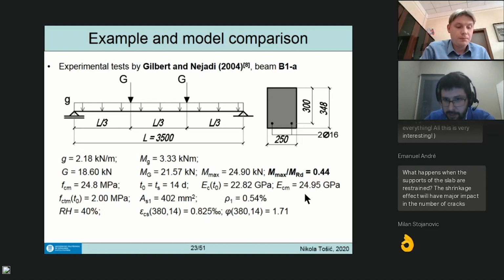Modulus measured at 14 days and at 28 days. Tensile strength measured at the time of loading, splitting, or we can approximate it to axial tensile strength. Reinforcement ratio of 0.54%. So it's not really like slabs, but it's not such a high reinforcement ratio.